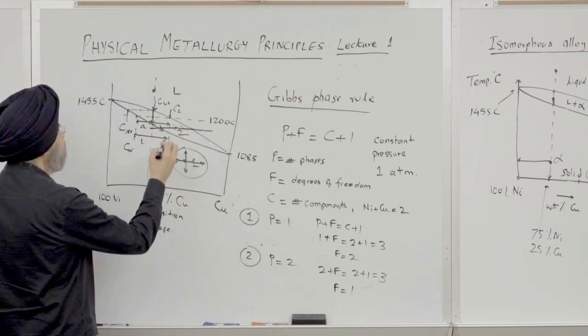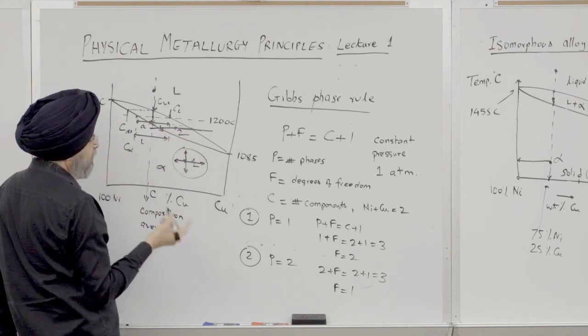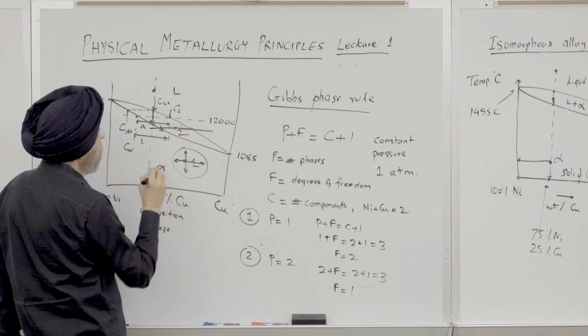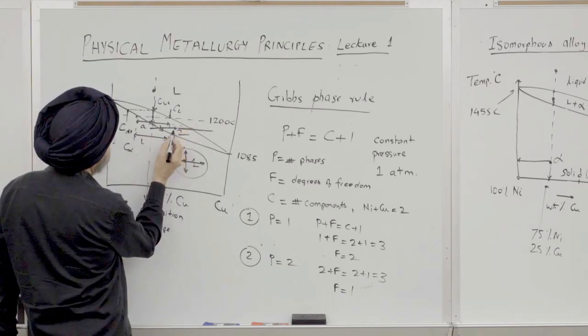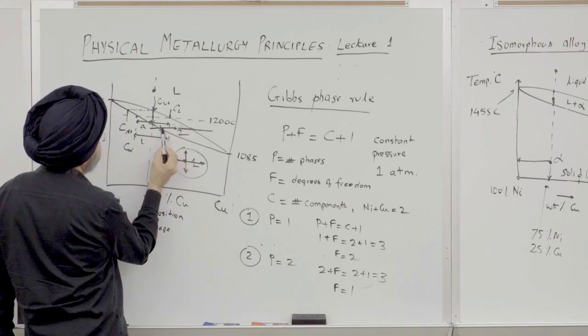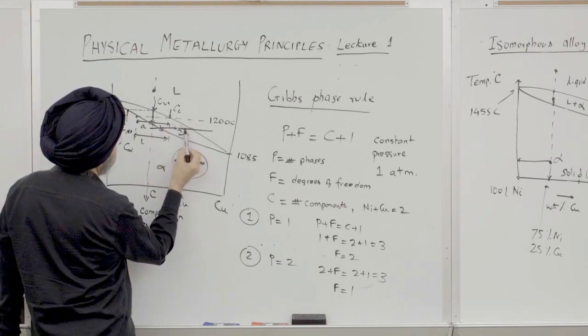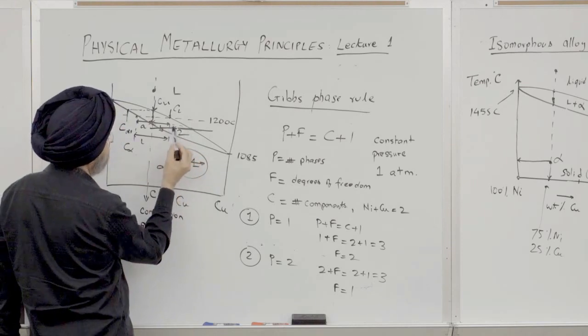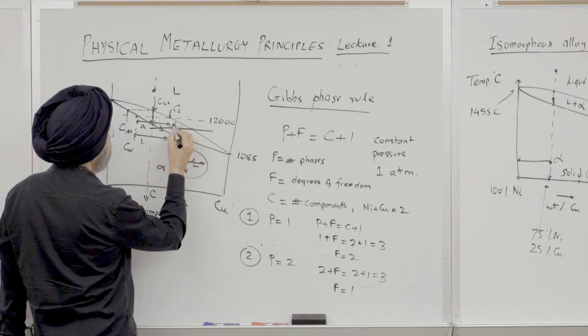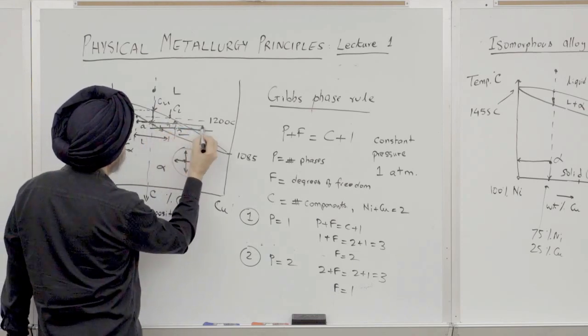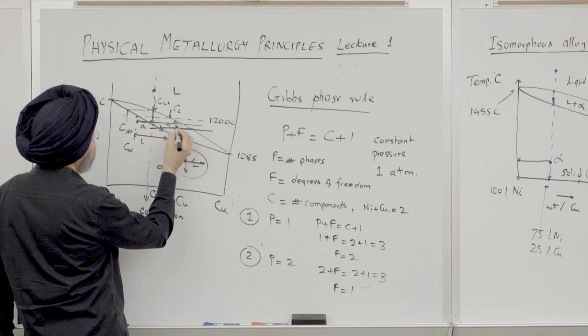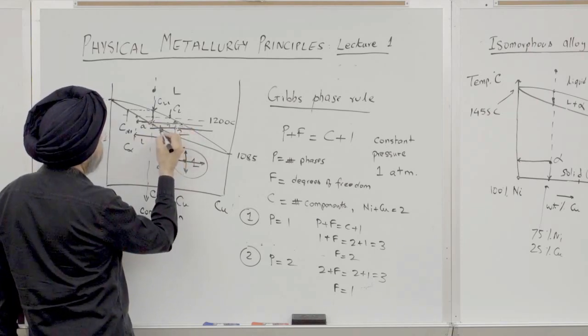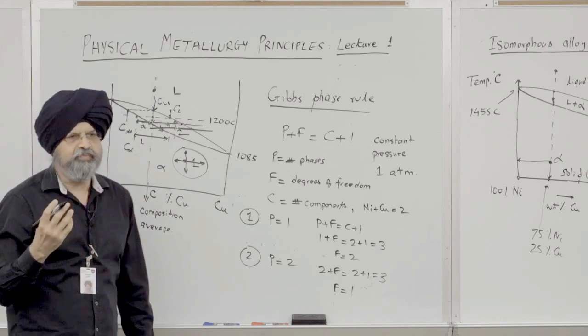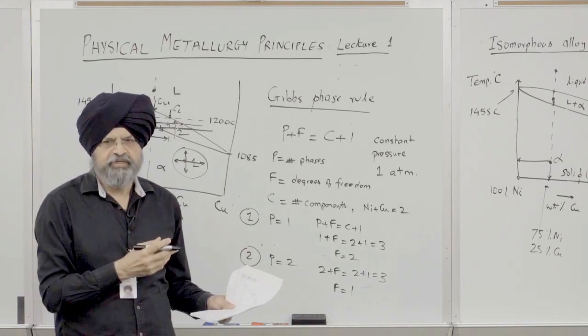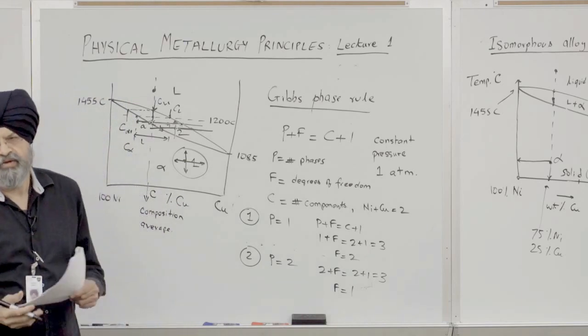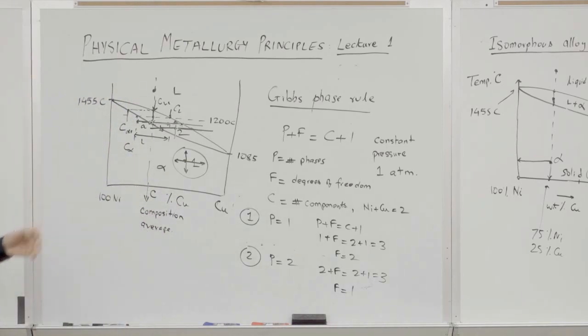What that means is I can only change one thing at a time independently. On this axis, I can change my composition, right? I can go along this way and nothing changes, the number of phases stays the same. And if I go vertically, if I change temperature, I get a new line. I change my temperature, but that also changed my composition. So I can only change one thing independently. If I change the temperature, then my composition changes. I can only make one change independently. The second change depends on the first change.